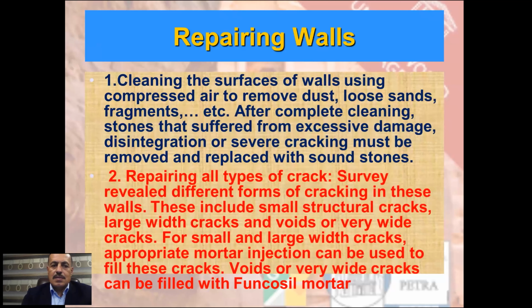Also, a detailed procedure for cleaning and repairing the walls: cleaning the surface of the wall using compressed air to remove dust, loose sands, and fragments. And after complete cleaning, stones that suffer from excessive damage, disintegration, or severe cracking must be removed and replaced with sound stones. And here it might be debatable, but some of the stones are really beyond repair. They are damaged, and consolidation cannot do the job. So in some cases, we need to replace some of the stones.